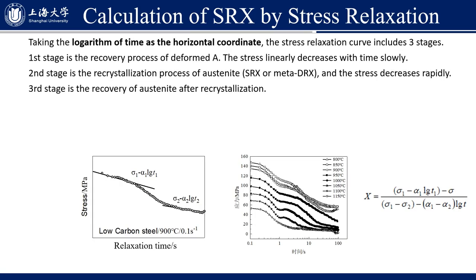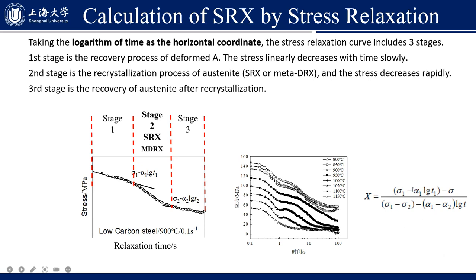Taking the logarithm of time as the horizontal coordinate, the stress relaxation curve includes three stages. The first stage is the recovery process of deformed austenite. The stress decreases linearly and slowly with time. The second stage is the recrystallization process of austenite, say static recrystallization or metadynamic recrystallization, and the stress decreases rapidly. The third stage is the recovery of austenite after recrystallization. And according to the equation here, we can obtain the static recrystallization fraction of the steel.